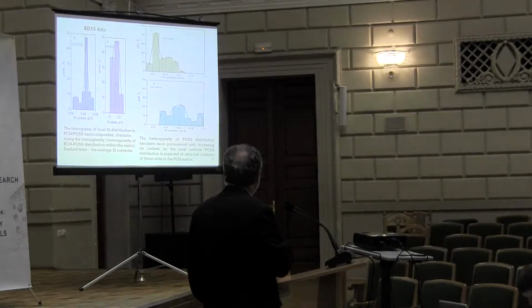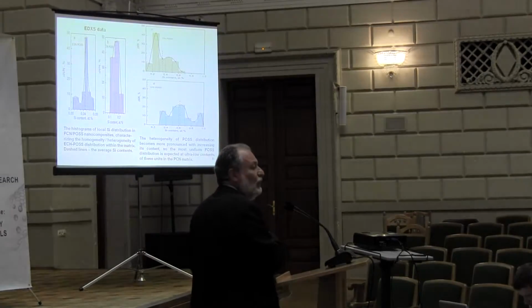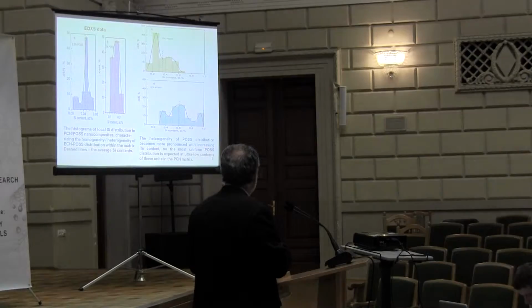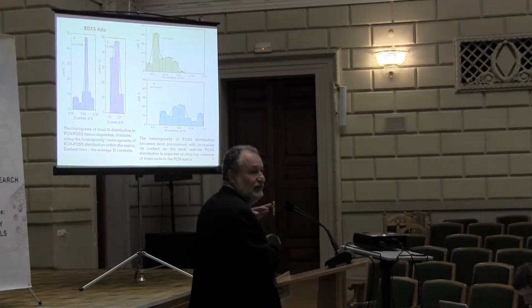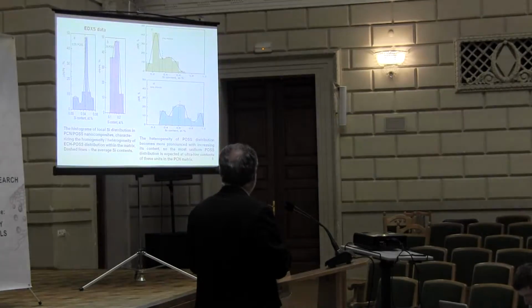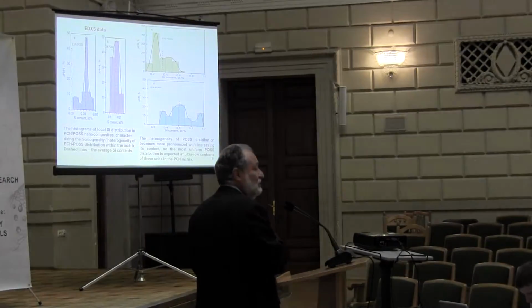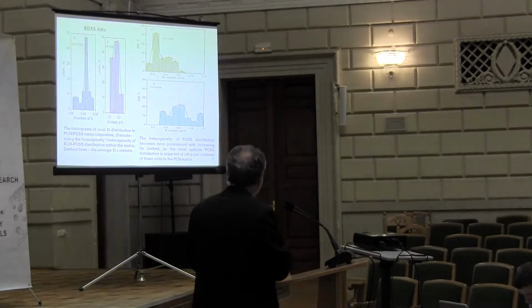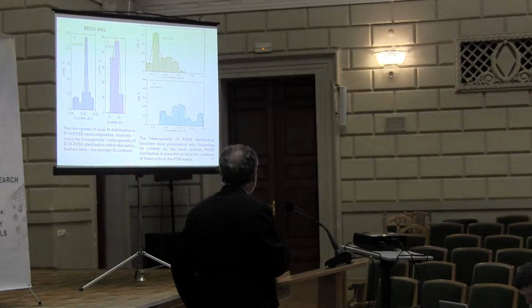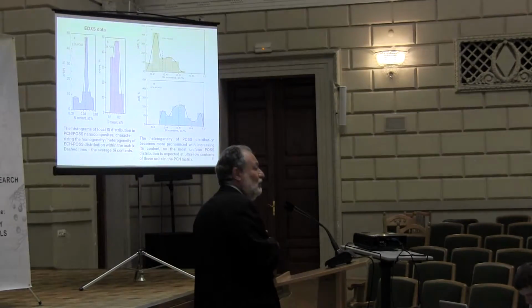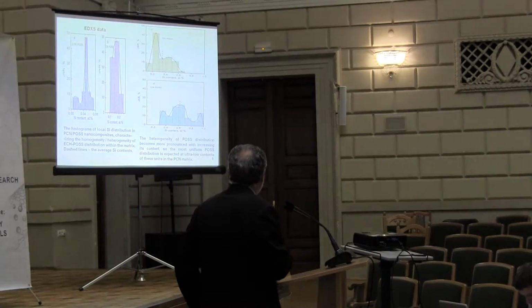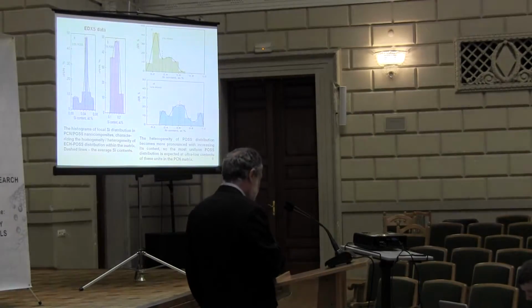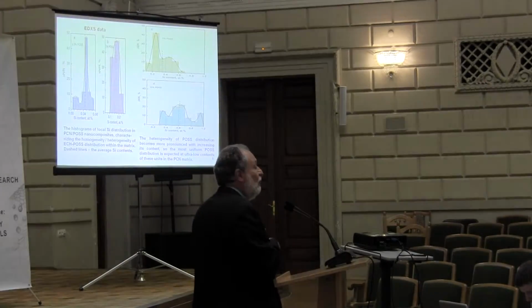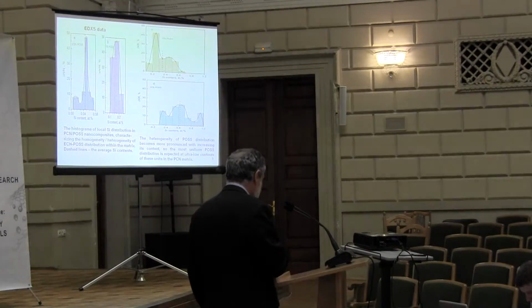And we were not able to have figures for ultra low amounts because the spectral signal is on the level of the noise. But we can imagine that the narrower the distribution, the better the dispersion, it will be fixed for the ultra low amounts, much lower than 1% of the filler. And also these results confirm formation of aggregates for high content like 10% of the nanofiller.